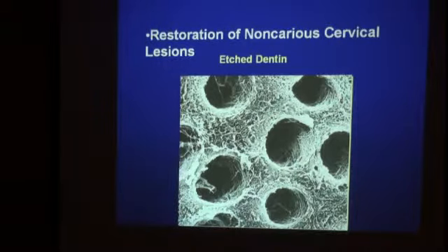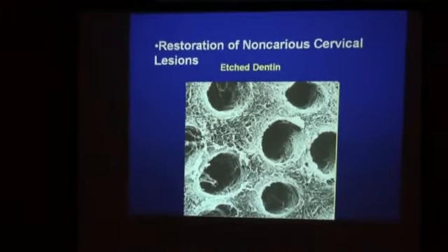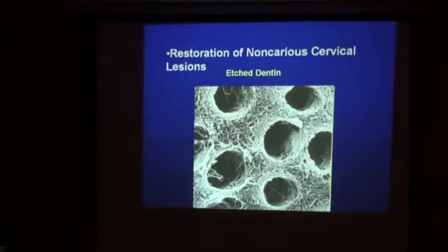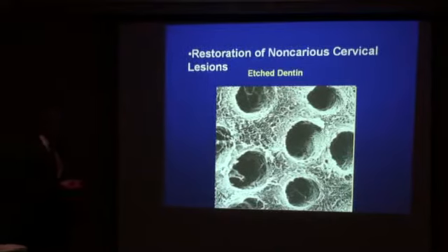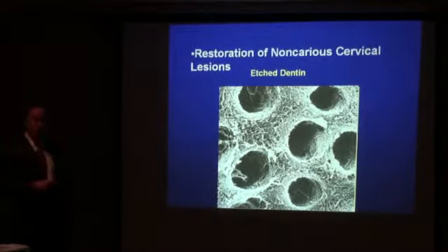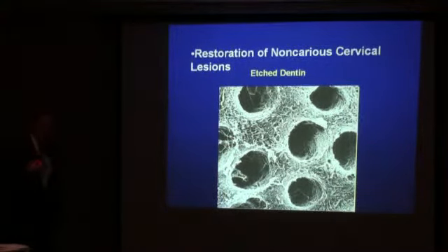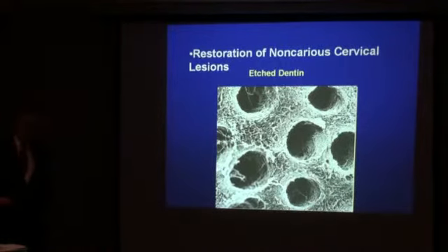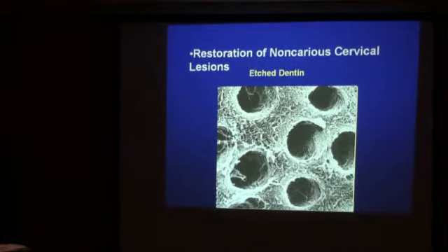And sclerotic dentin doesn't etch. It doesn't etch well. You don't get this type of appearance with sclerotic dentin. So you don't have the ability to achieve mechanical retention like you do in normal dentin. And that's why the authors surmised that 1/3 of the composite resin restorations were lost after 2 years.